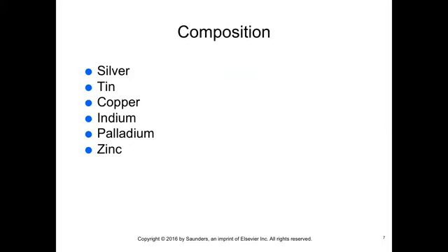Dental alloys for amalgam are composed mainly of silver and tin. Copper is added to replace some of the silver to lessen the brittleness. Modern dental alloys are considered to be high in copper content, usually 13 to 30%, compared with their predecessors, which had 4 to 6% copper by weight. They generally contain 40% to 70% silver and 12 to 30% tin.